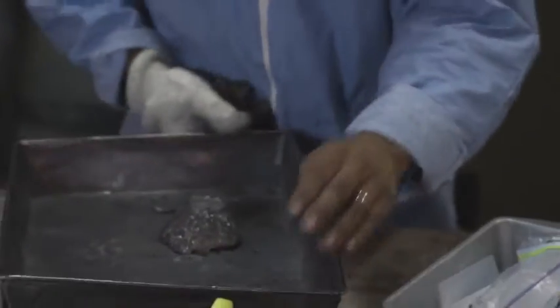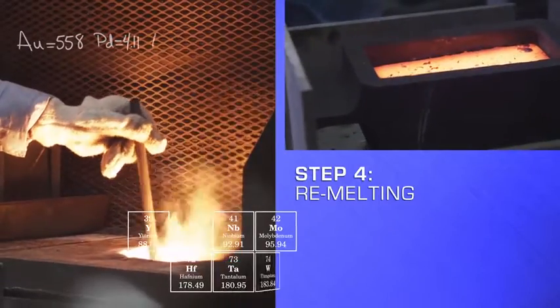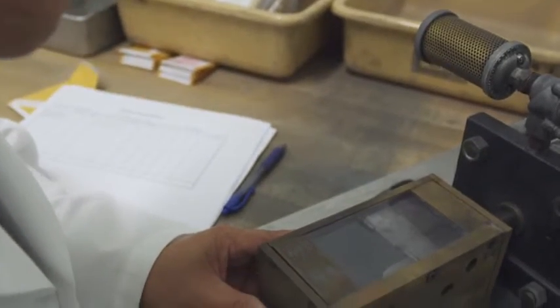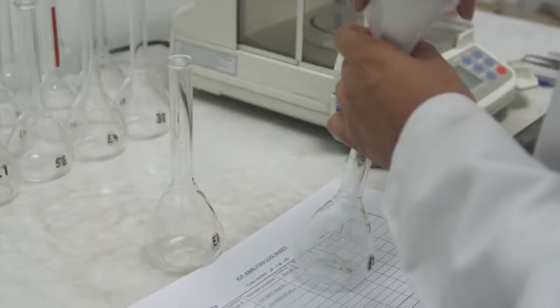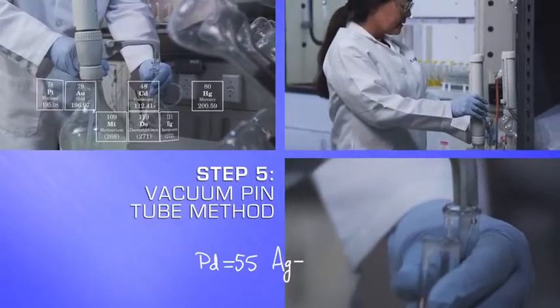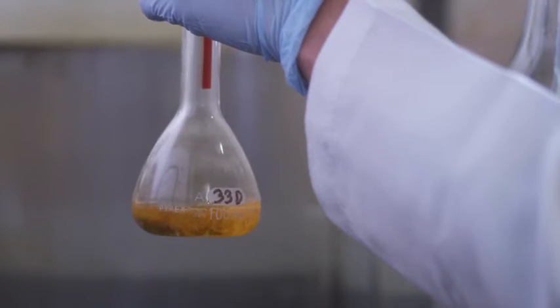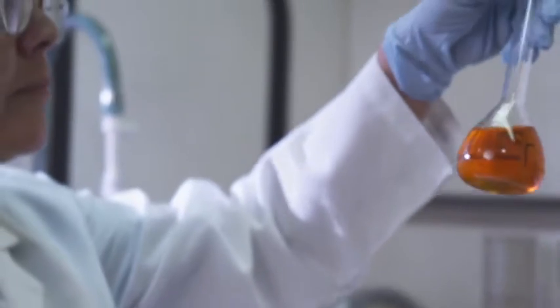The flux is then separated from the metal and the metal is remelted using an induction furnace in order to take a sample. We make sure that no metal is left behind. We use the vacuum pin tube method to extract a completely homogenous sample. Three samples are taken to ensure consistency.